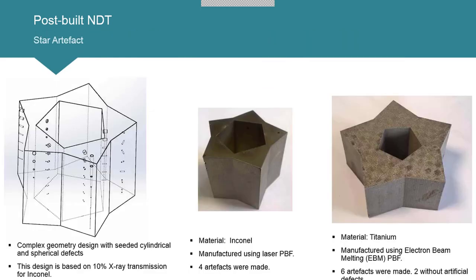Now, for the standard, we have created an artifact, as you see there. We are covering the post-build NDT section, and we decided on a somewhat complex design, but with areas that we can define with different kinds of defects. In some of the areas we have horizontal cylinders, and then we have our vertical cylinders. Those were seeded, mimicking the types of defects which are layer defects or cross-layer defects vertically. And then we have spheres, which basically trap powder, and we also have cylinders which trap powder at different angles.